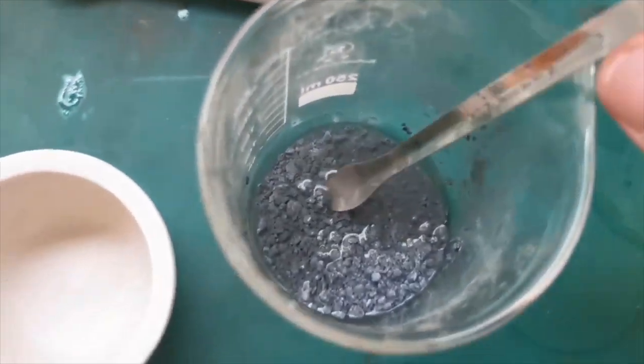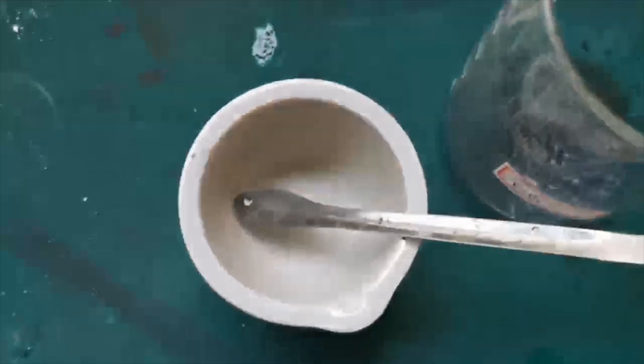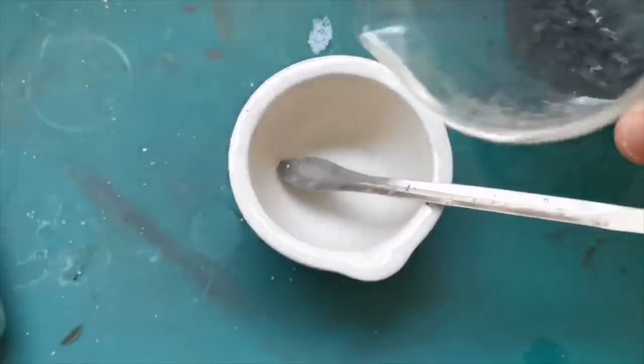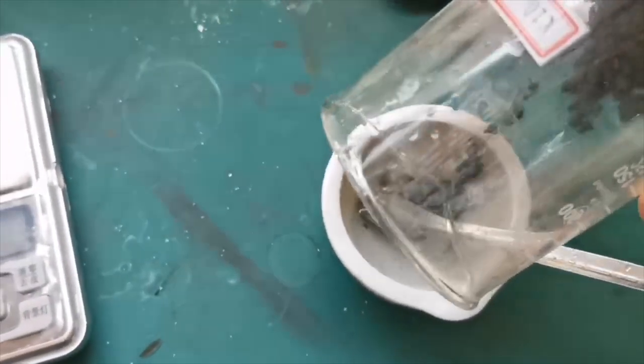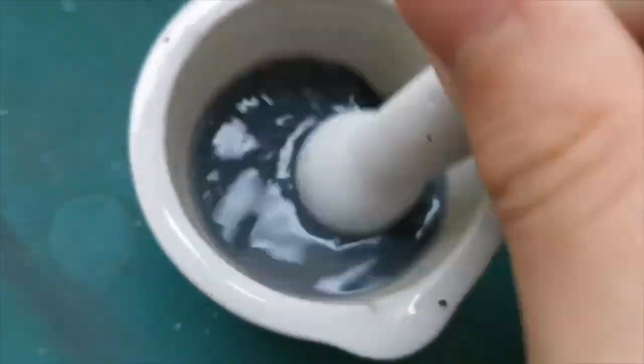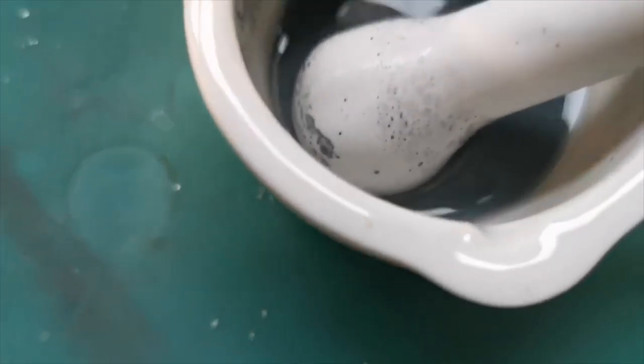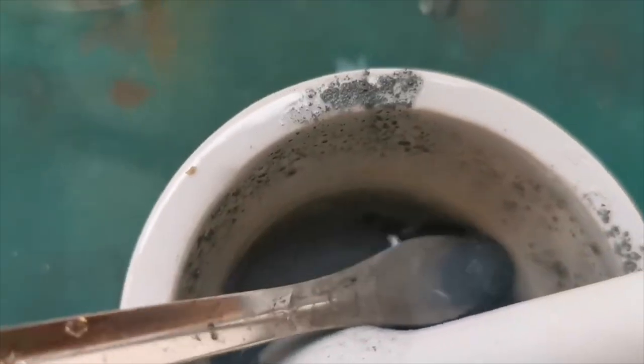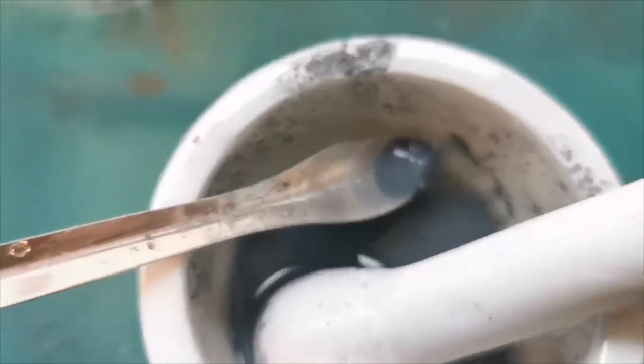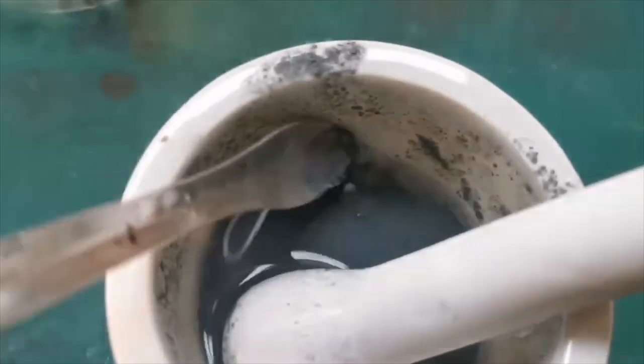The zinc is then washed three more times with 99% ethanol to remove the residual water and transferred to a mortar on the last wash. It was then ground with a pestle for a few minutes. Here, I used a spatula to scoop out some zinc and there were no obvious clumps, which tells me that it is already finely ground.